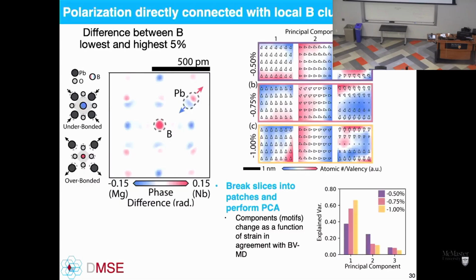But what this allows us to do is look at how, if it's more niobium rich, that would be more red basically, you get displacements of lead being pushed out and oxygen being pulled towards that middle lead, or the middle B-site cation. As it's more positive, it wants to drag in the negatively charged oxygen. The positively charged lead wants to go away. And so you can get this chemical information directly from these maps on a very local basis. These are unit cell level displacements.